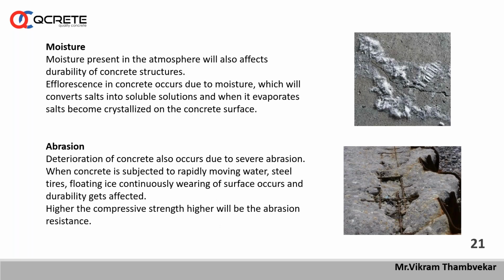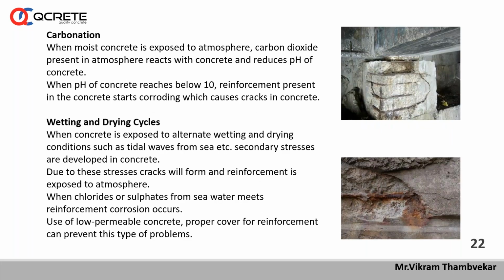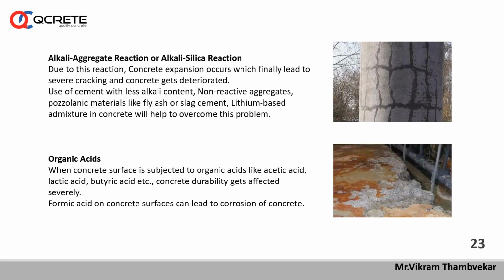Then other factors affecting the durability are moisture content, abrasion, carbonation, wetting and drying cycle, alkali aggregate reaction, and silica alkali reaction. See, in the Mumbai region and in most parts of India, apart from North India, we are getting very good quality of aggregates for making fresh concrete. Here we find better quality of aggregates as basalt stone is available, whereas in the North region, at many places, the stone quality of aggregates is not good.